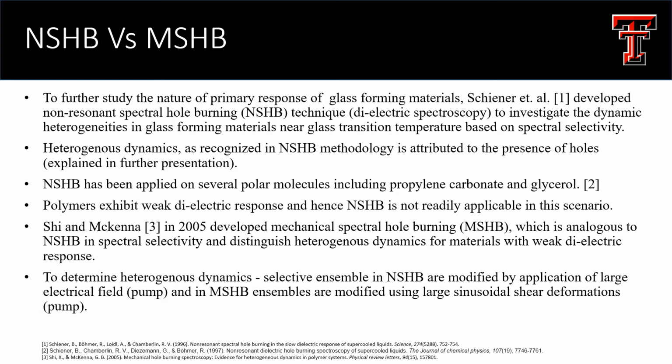The idea of NSHB is to devise an experimental technique that allows the distinction of heterogeneously and homogeneously broadened spectra, using spectroscopic means to monitor local subsets of the relaxing species in the supercooled liquid state. Heterogeneous dynamics, as recognized in NSHB methodology, is attributed to the presence of holes, which will be explained later in the presentation.